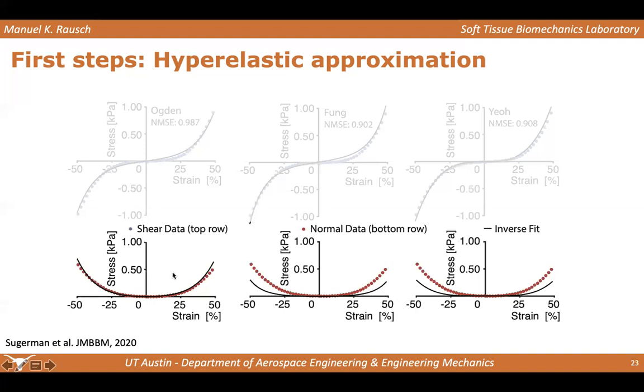It turns out that the Ogden model just did a much better job in capturing the normal stress as opposed to the Fung model or the Yeoh model. And so moving forward, we'll be using the Ogden model.